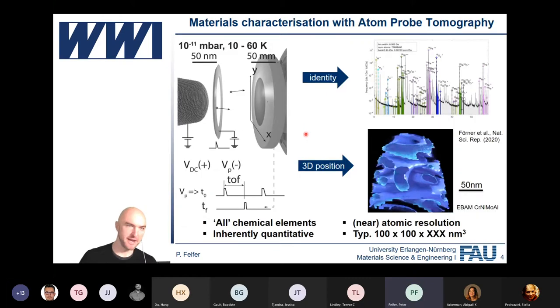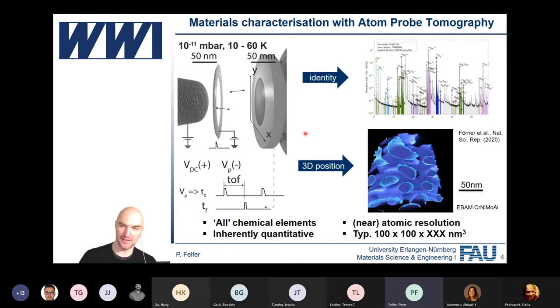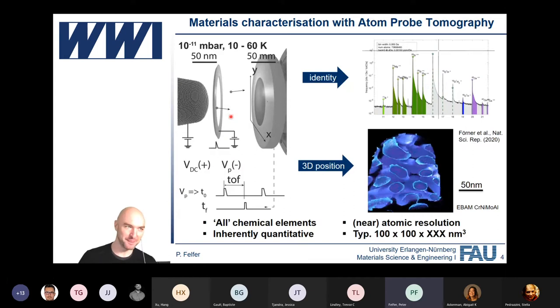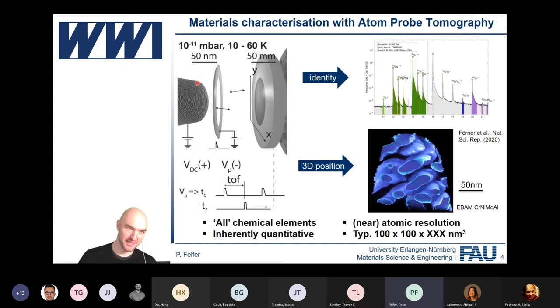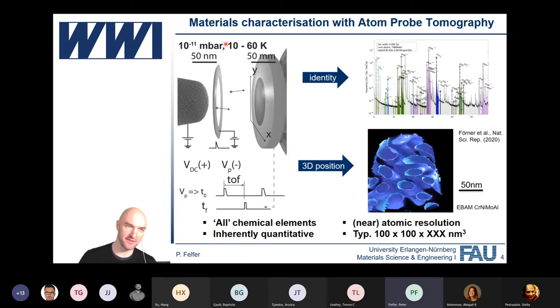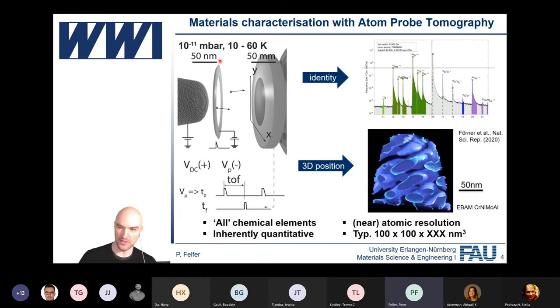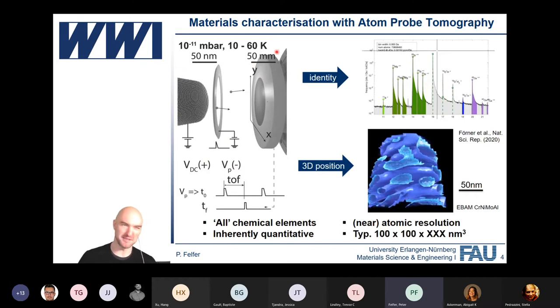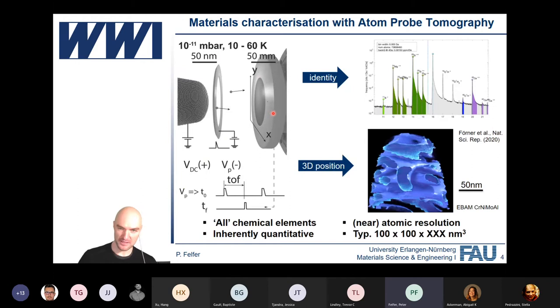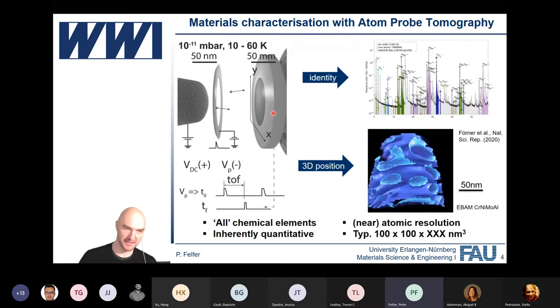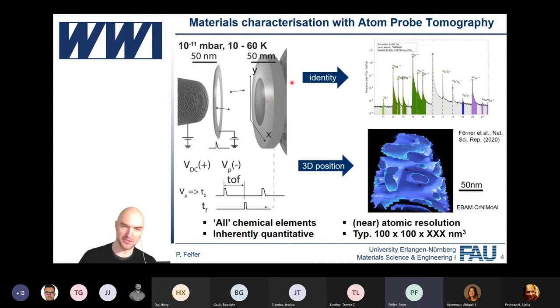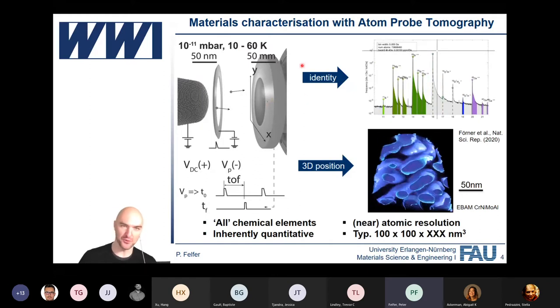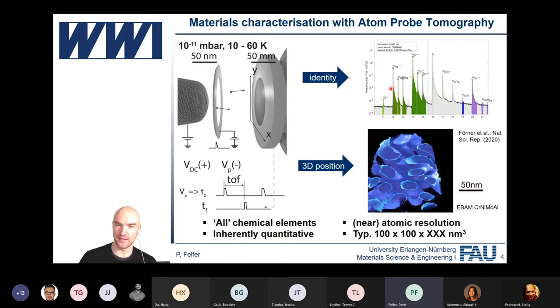The thing about atom probe tomography is I'm pretty sure by now you're fairly familiar with the principle — you've been successful in getting quite a stellar set of equipment into Imperial as well. The boundary conditions are that we operate at very high vacuum — ultra-high to extreme-high vacuum. Our machine is the first one now operating extreme high vacuum, below 10 to the minus 11, and usually between 10 and 60 Kelvin. This is not really an environmental condition, and we want to get as close to those final measurement conditions in our transfer as well, so we can stabilize certain material states.